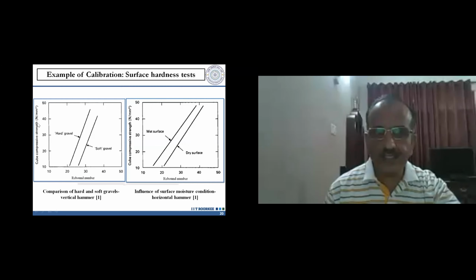This is just to quickly show you the influence of aggregate type on the calibration chart. This is a calibration chart between cube strength and rebound number. You can see, if you're using hard aggregate and in the calibration soft aggregate was used, both values will be different. The same rebound number of 30 will give you different strength values. The same is true for wet and dry surfaces also. So you have to apply a correction for moisture also, as I said.